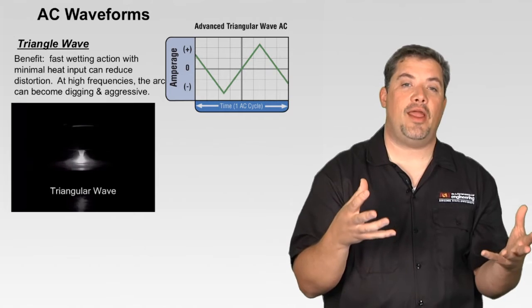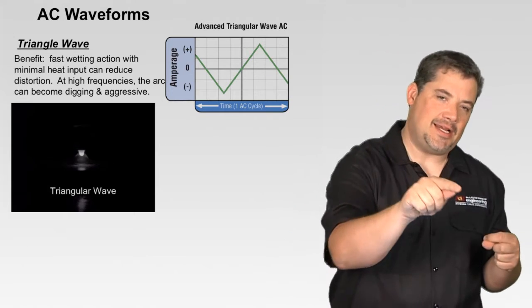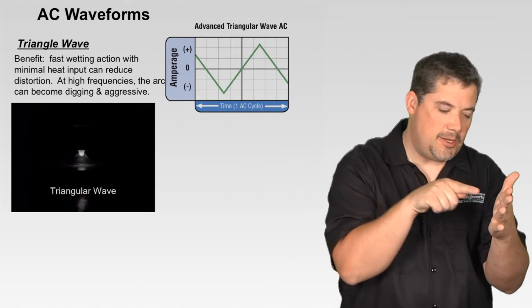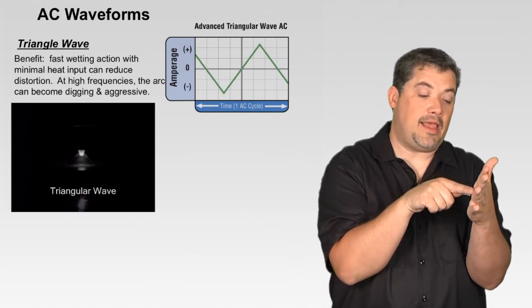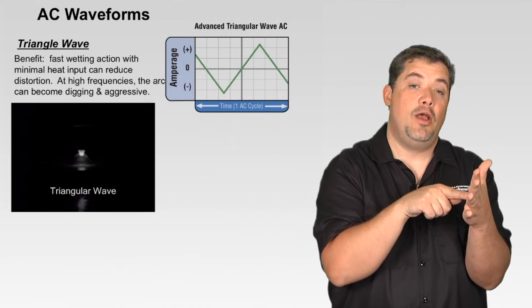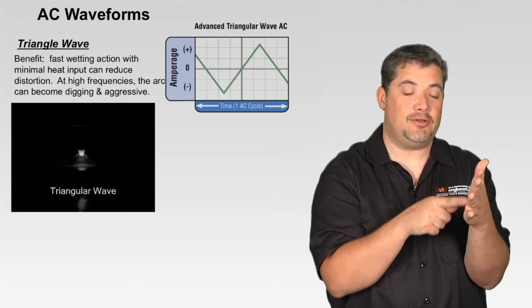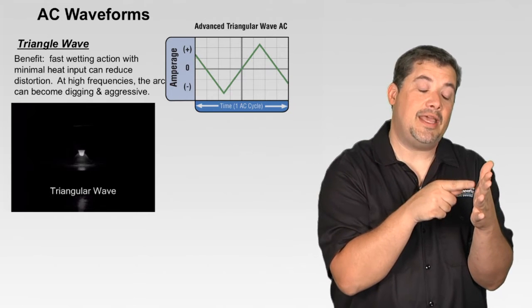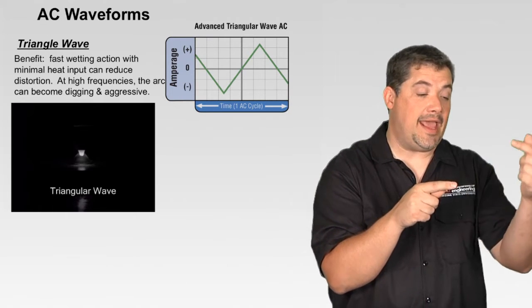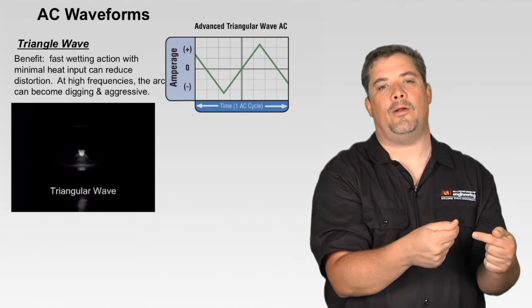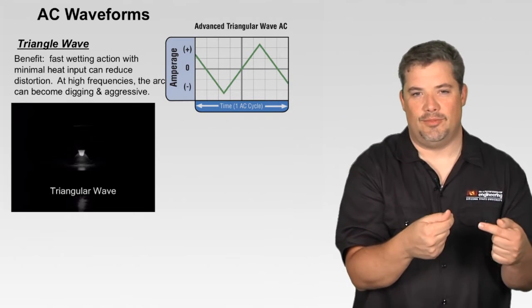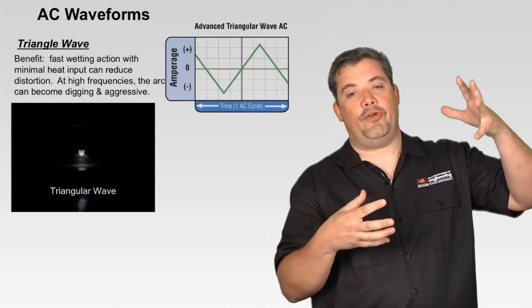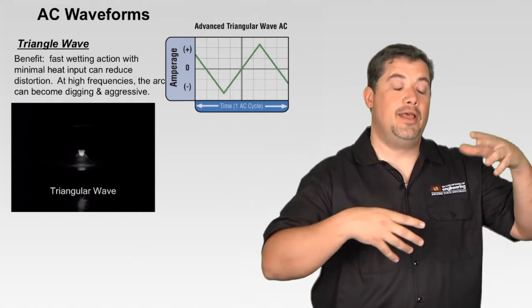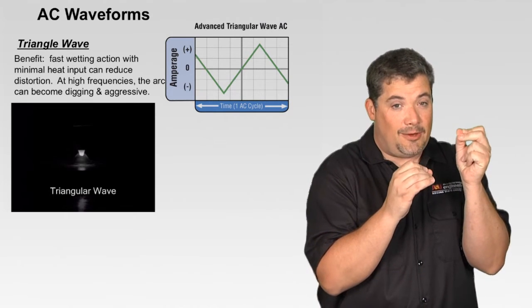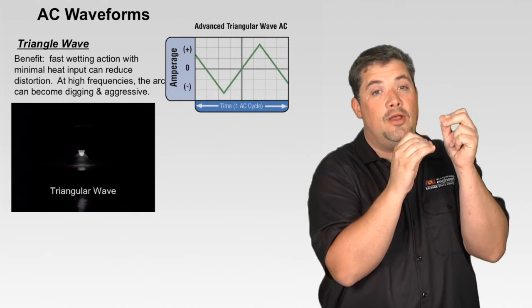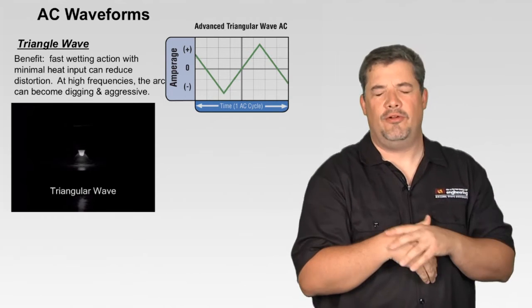Well, when I use that triangle wave, that instant in time that it's at a high amperage just punches right into that corner to get that root penetration that I need without overheating it, because on these aerospace tests, not only do they got to get into that corner perfectly, they can't melt through the backside at all on the parts. So with a conventional machine, it would take them forever to get the whole fixture hot, the whole part to get hot, just to try to maintain this tiny little puddle that gets adequate penetration without getting too hot and melting through. Very difficult test.